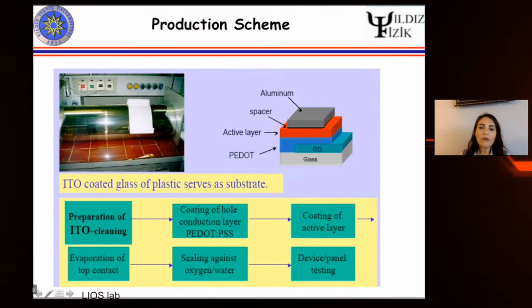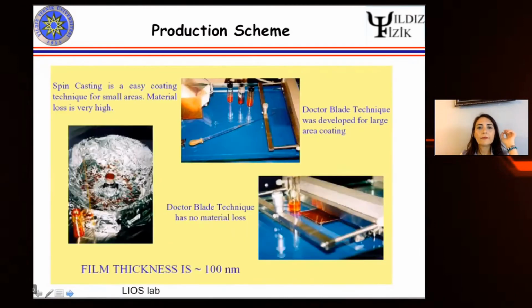These pictures I took from LIOS lab where I was during my PhD. So this is the ITO preparation. We need a clean substrate. So preparation and ITO cleaning is part of this production scheme, and then coating of this hole conducting layer, PEDOT:PSS, coating of the active layer, evaporation of the top contact, and we need a kind of sealing. I'll be explaining this in detail, and then we take this device for testing. At least this is for the laboratory scale.